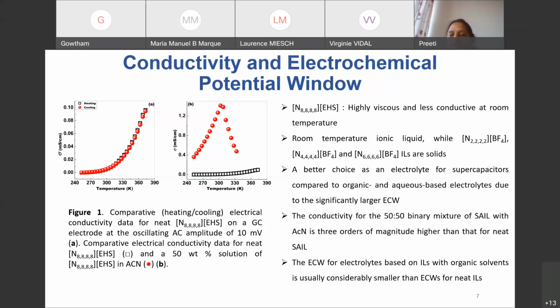So we can add any organic solvent to it. Even though that was not the purpose, it was just to check how the organic solvent affects their physicochemical properties like conductivity and electrochemical potential window. So we have simultaneously measured the binary mixture of the surface active ionic liquid with acetonitrile. And as you can see here, a huge difference in the conductivity has been observed.